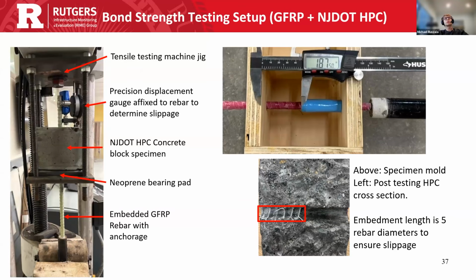So going into bond strength testing, we ran bond strength testing in our lab. We made a tensile testing machine jig, and it uses a precision displacement gauge to measure slippage. We use NJDOT concrete specimens with the embedded GFRP rebars with anchorages, and you can see the setup on the left and the sample setup on the right. Only a portion of it is bonded to increase the accuracy of the test.